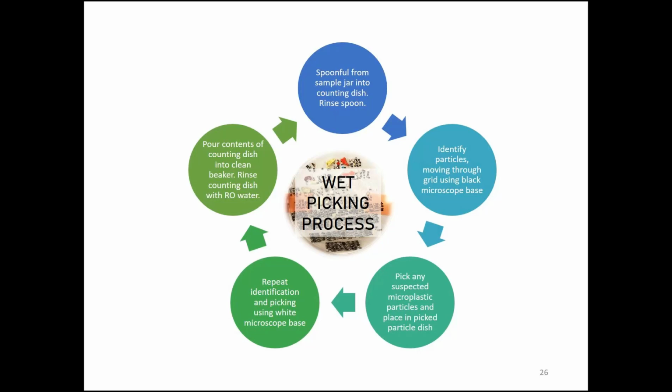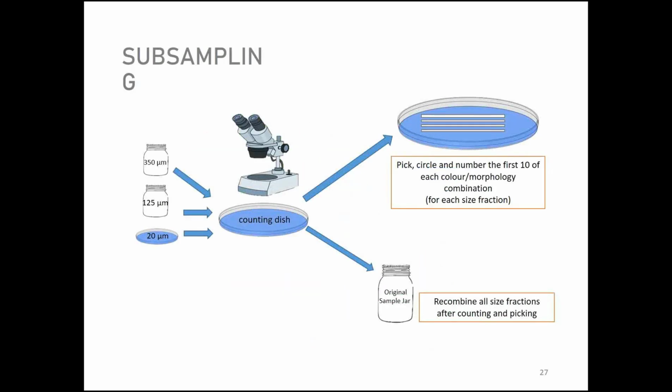So this is laborious. Go to the next slide. When we are picking the plastic and putting it into the particle dish, in the beginning of this study, we were actually picking every single particle, and we tend to mount them on double-sided sticky tape. That is because we are prepping them for Raman spectroscopy, and for our instrument, that's the best presentation method that we have, besides a filter. And in many cases, this mounting works really well because it keeps the fibers steady, for example. But this is really laborious.